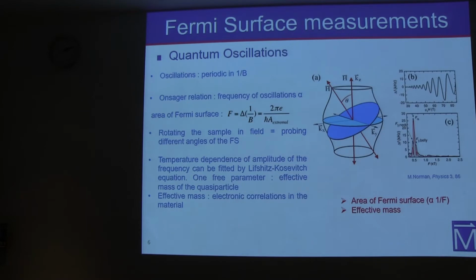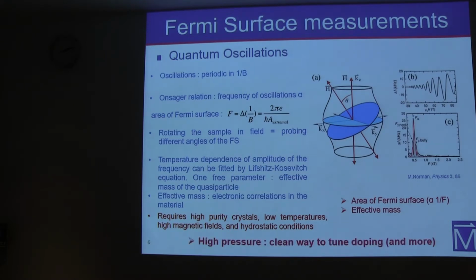Those are the two main things that we get from quantum oscillation measurements: the area of the Fermi surface and also the effective mass of the quasi-particles. The trick with those measurements is that they're not easy. You need really high purity crystals, because any type of disorder will prevent the electrons from going into cyclotron motion and prevent any oscillations. You need very low temperatures. The higher the field, the better the oscillations. You need to go oftentimes to high field facilities. And for pressure measurements, you need hydrostatic conditions, and I'll talk more about that later.